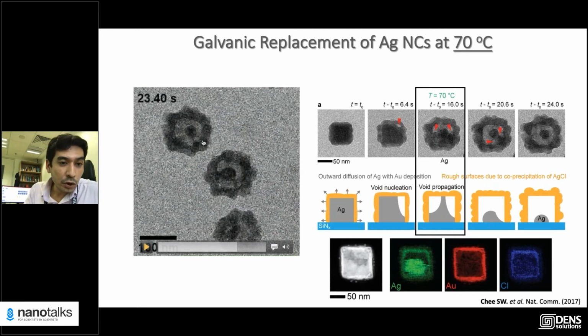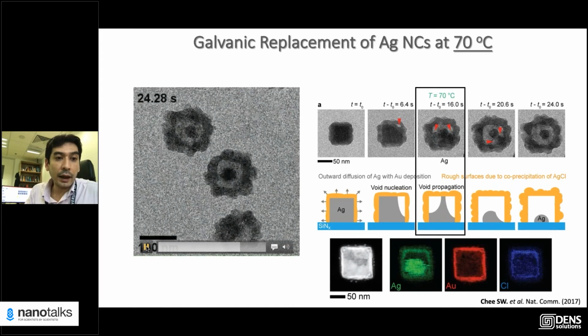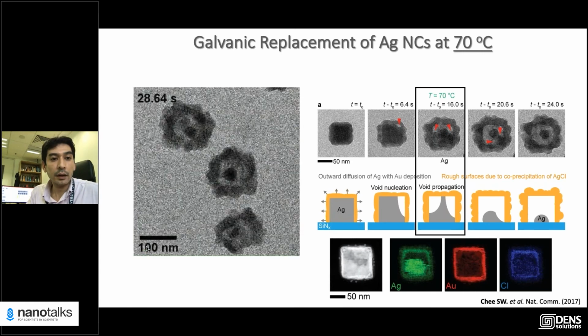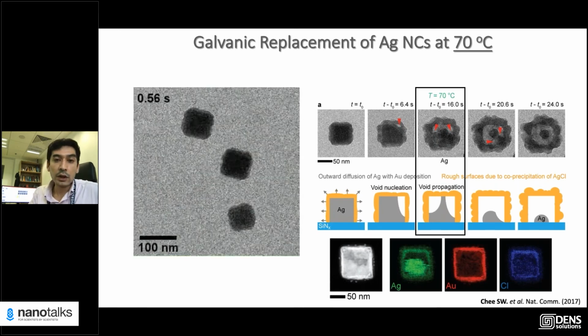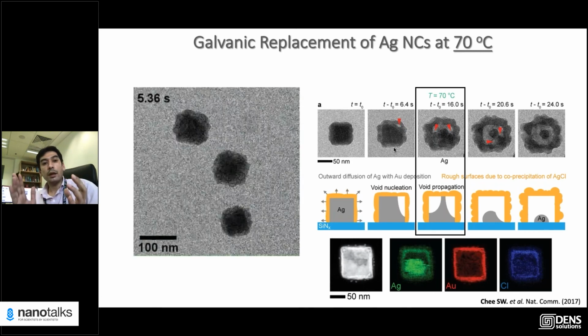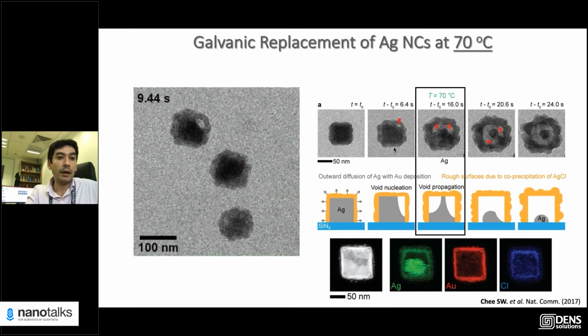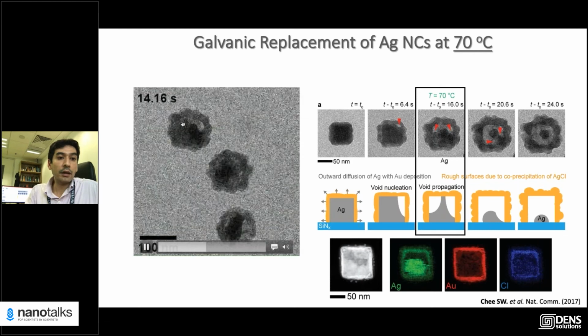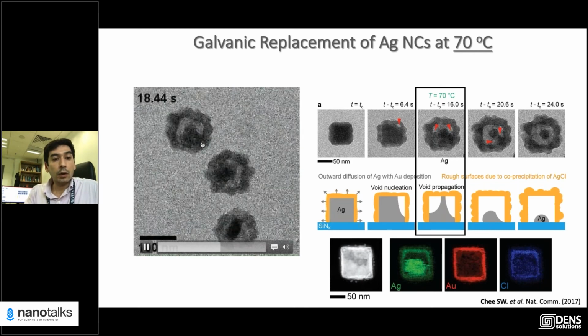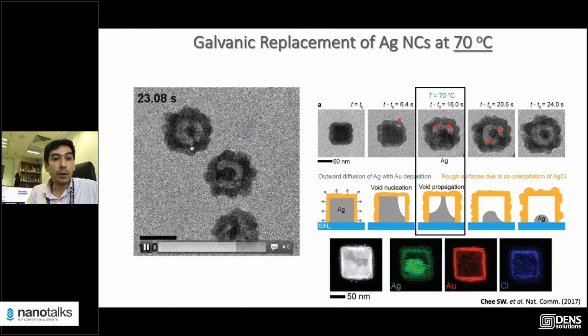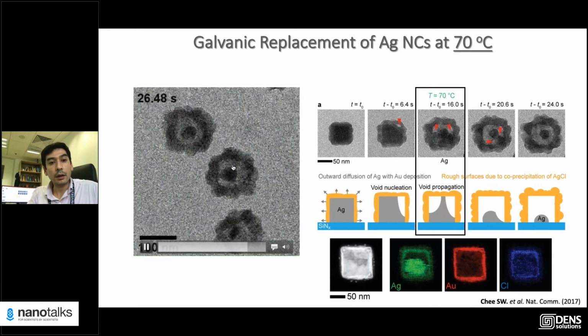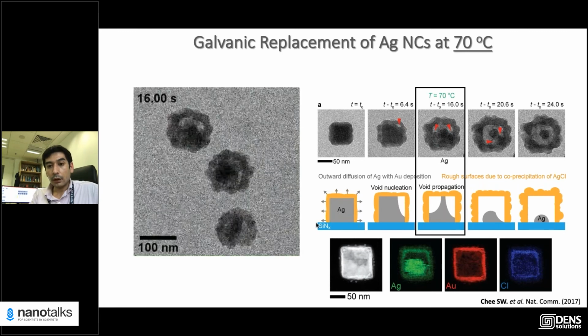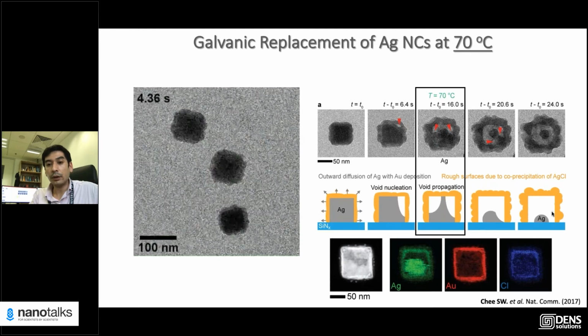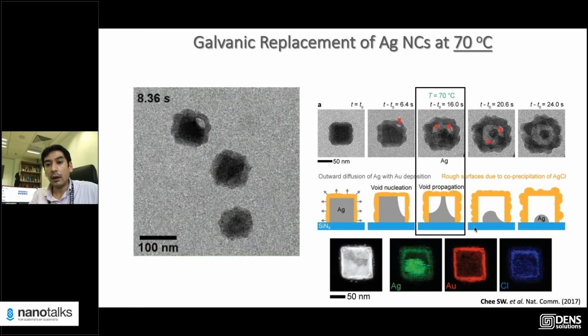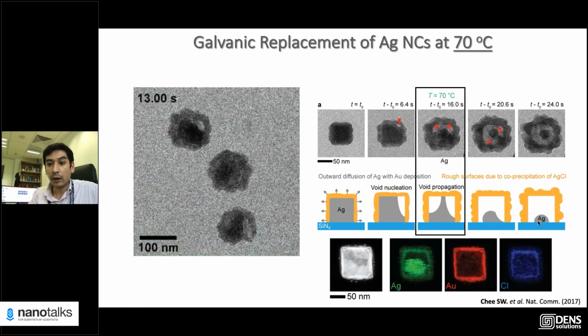And what you have next is this particle detached. That's the core detached. The core, the silver, is detached, and nothing happens until the particle falls apart. And then after it falls apart, it's going to etch, but nothing happens before that, right? The particle's interface detached from the shell, and nothing happens. Now it's just eating it away. So what's happening is the silver is diffusing out through its contact to the deposited shell, and once this contact is broken, the core silver remains in place. So that's why you end up with this kind of structure. If it was etching through a pit, you would not stop at this point of the reaction when you have just detached silver.